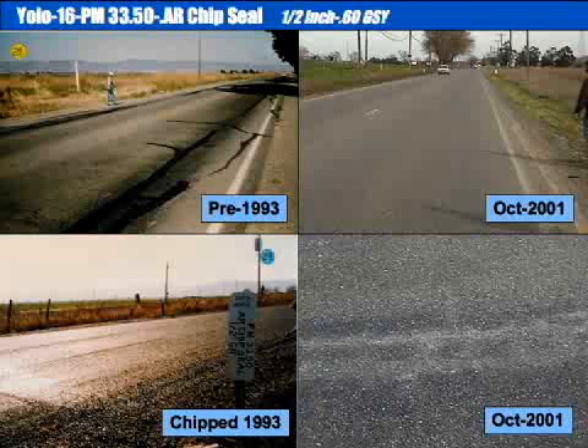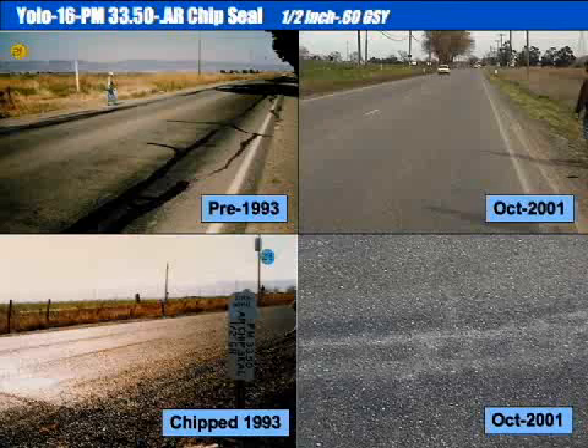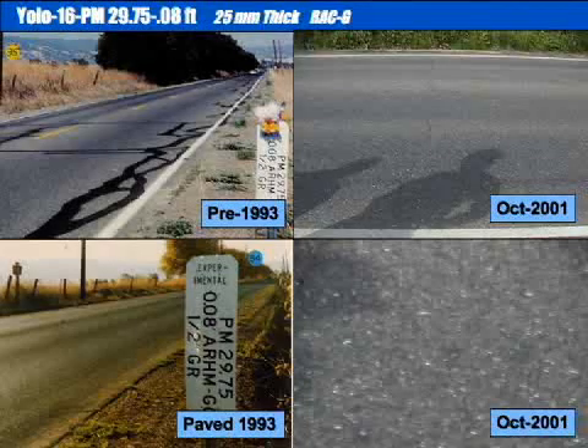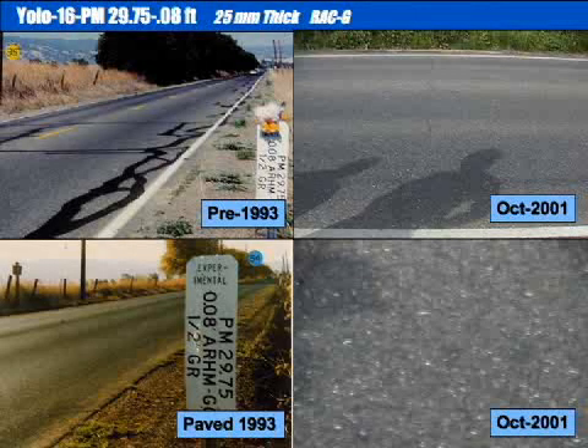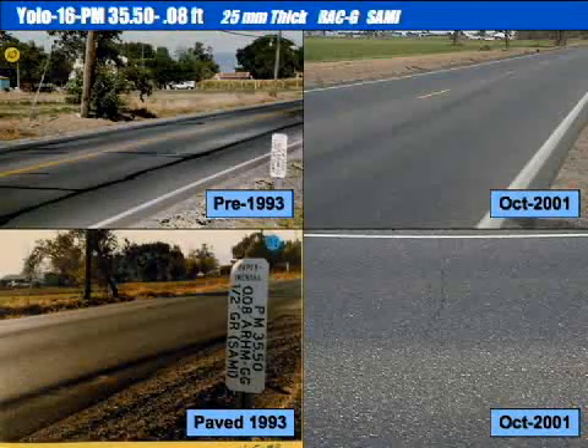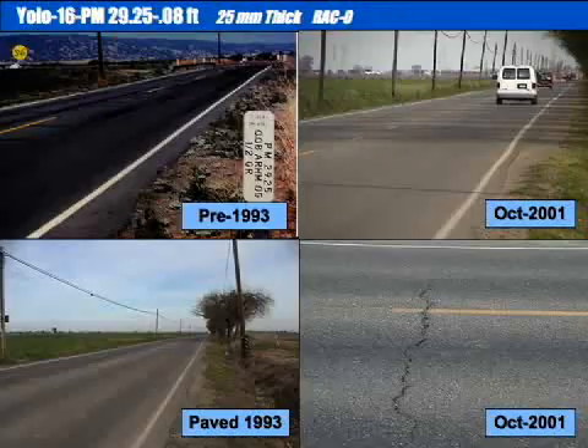So the 1993 compared to the 2001, you see the difference here for a half inch maximum size for an asphalt rubber chip seal. The performance was excellent. Here is also another project, the gap graded, 25 millimeters, good performance. And this is the gap graded with a SAMI, which also shows a better performance than the one without SAMIs.